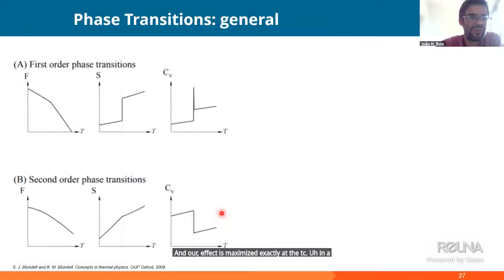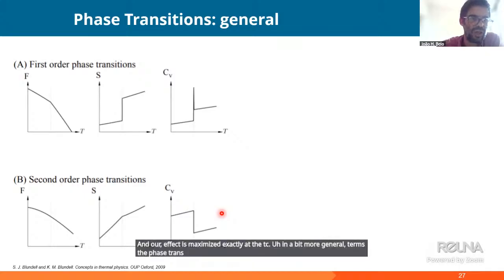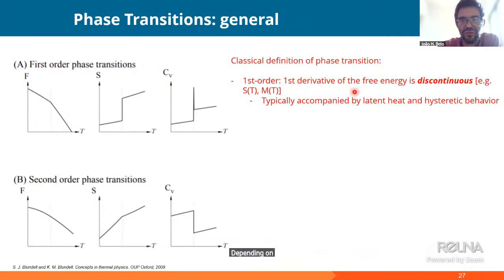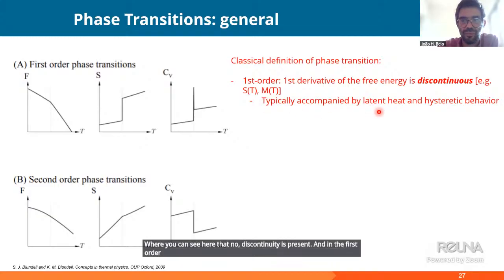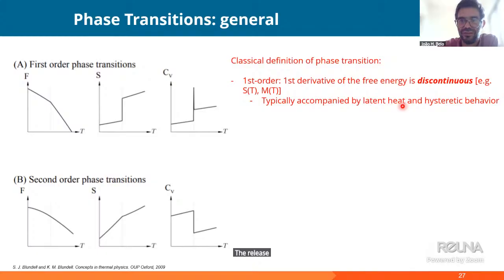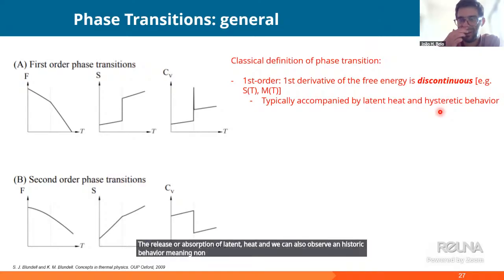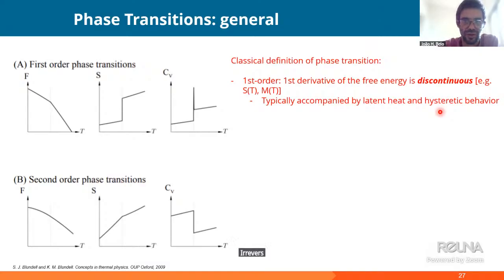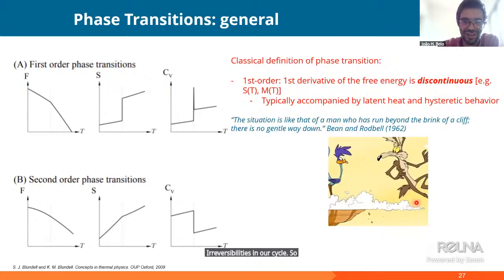In a bit more general terms, the phase transitions can be generally classified into first and second order, depending on if their first derivative of free energy is discontinuous, like here, in contrast with the second order, where you can see here that no discontinuity is present. And in the first order, typically happens the release or absorption of latent heat, and we can also observe a hysteretic behavior, meaning non-reversible irreversibilities in our cycle.